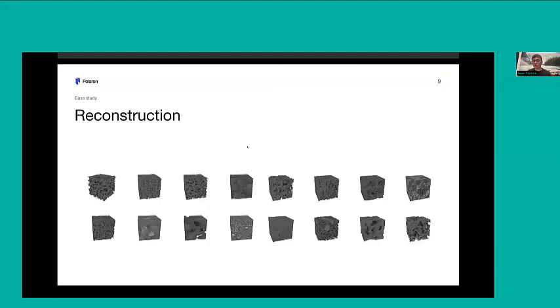And we've applied this to a very wide range of materials. So I've focused mainly on battery materials so far, but we applied this exact same technique across a large database of metal alloys, composites, ceramics, and we found that the technique performs very well. And we did some validation of these reconstructions, and the validation we do is we take a 3D image, we take a slice through it, we train our model with that slice, we compare the reconstruction to the ground truth 3D, and we look at the statistics, and we see that there's incredibly good agreement.